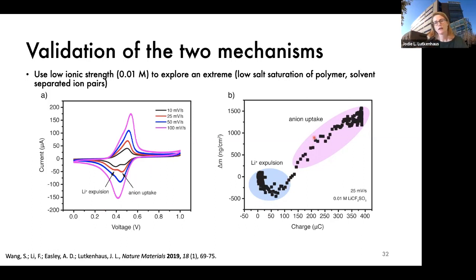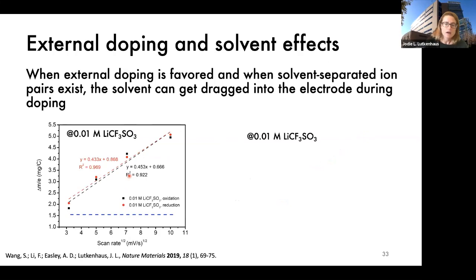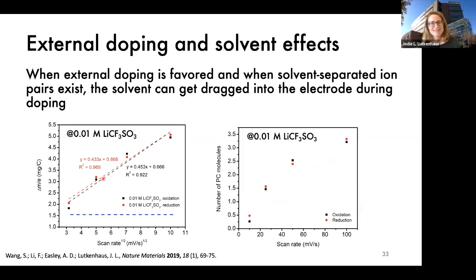Then we plotted delta M versus Q, which is a running integral of the oxidation plot. We can see that when we go through the lower potential peak, the mass actually decreases. That's affiliated with the lithium cation getting kicked out of the electrode, as we described in the first case. And then anion uptake takes over, which is the original case we were assuming. So now that we've observed that, we can assign mechanisms to those two peaks. The other interesting thing is that at those really low concentrations, the electrolyte is solvent separated, so we have a lot more participation of the solvent and cannot ignore it anymore. Our observed delta M/Q value is much higher than theoretical. If you do a mass balance, you can estimate the number of solvent molecules that come in. At this particular scan rate, for every one triflate anion I bring in, half a propylene carbonate molecule, or really, for every two triflate anions I bring in one propylene carbonate. Obviously, there are a lot of assumptions that go into this calculation.